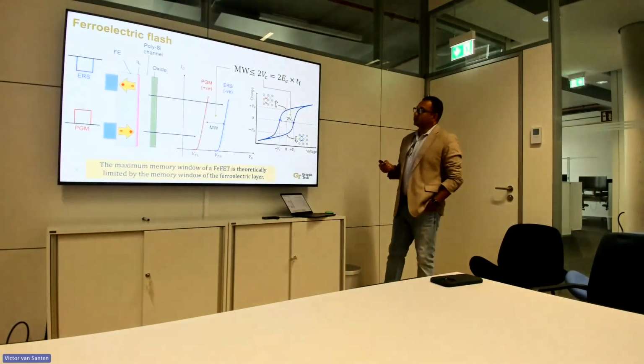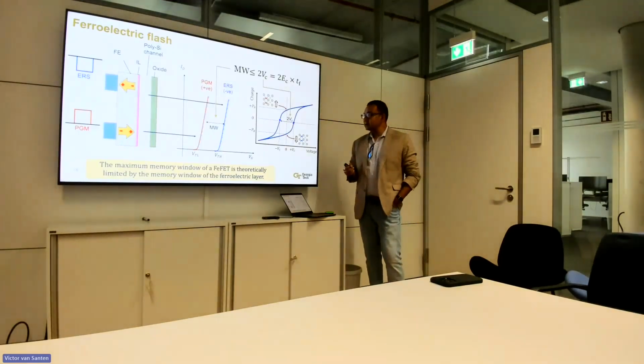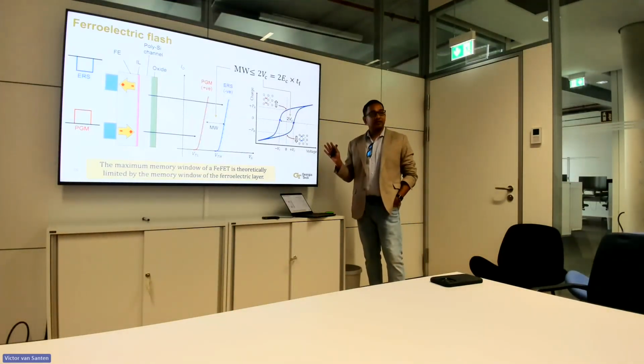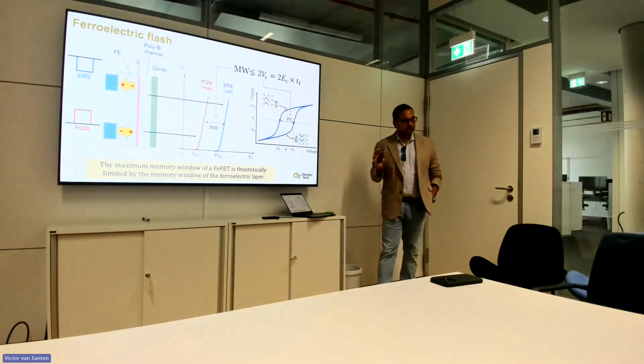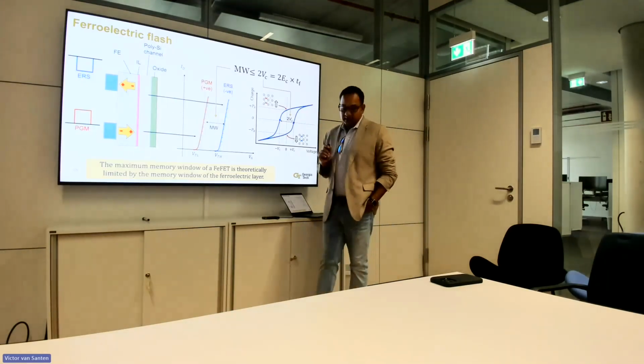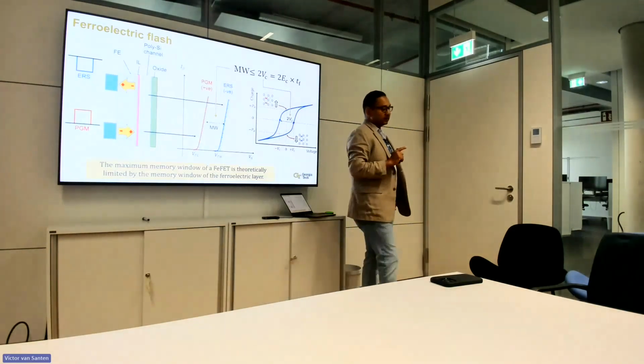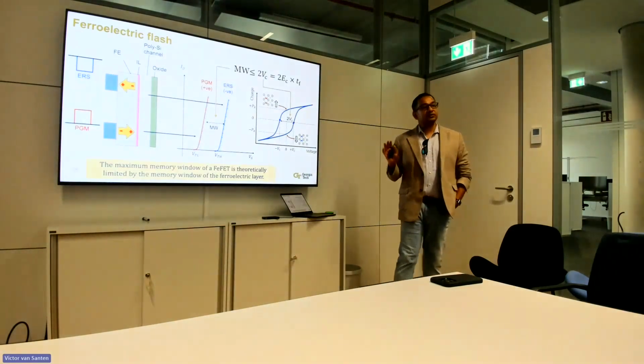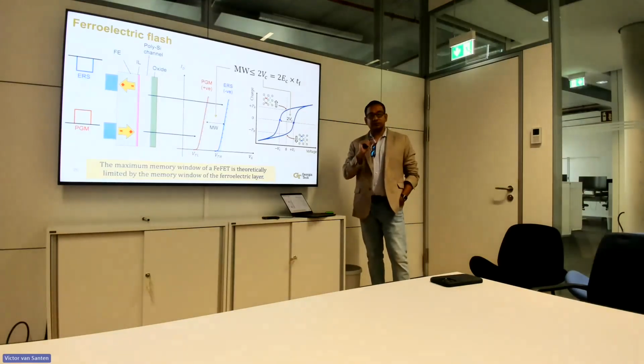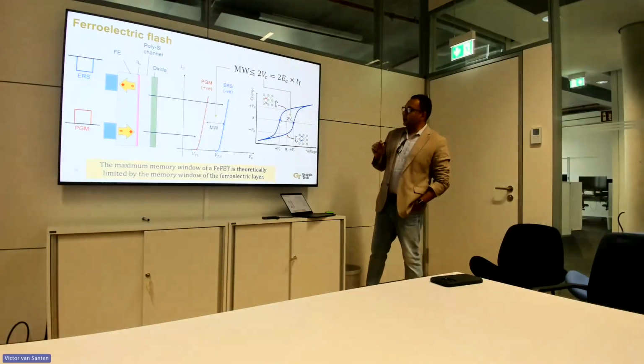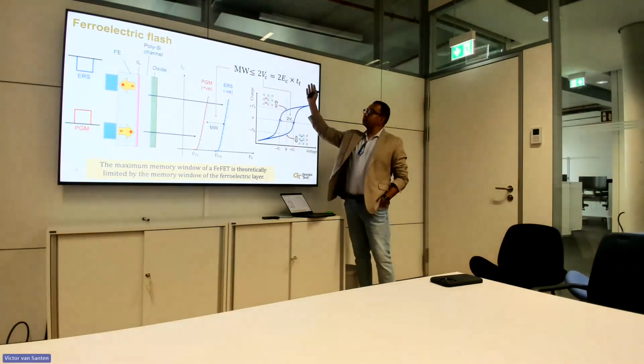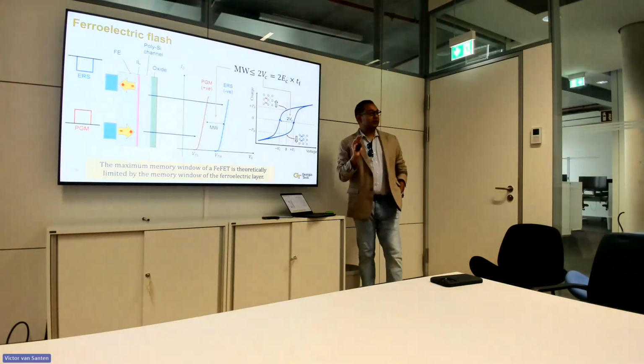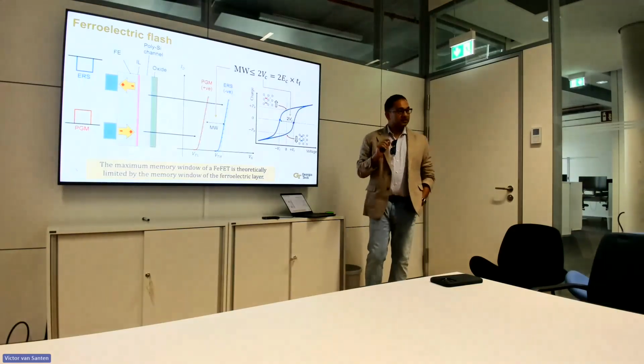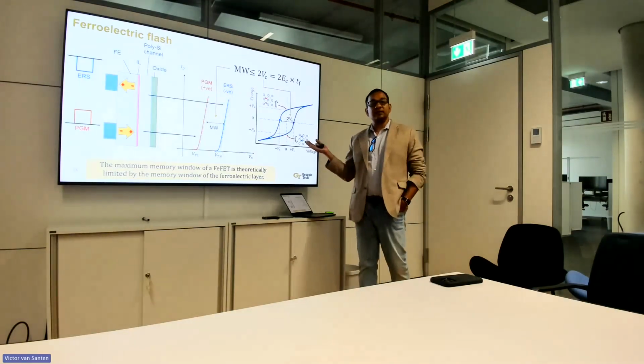Okay, so now before I get into the details, another thing is, what is the maximum limit of memory window that you can get out of a ferroelectric field effect transistor? The key thing here is that we want 7 or 6 volts of memory window with 20 nanometers of ferroelectric thickness. Now, for a long time, it has been known that the maximum memory window that you can get out of a ferroelectric field effect transistor is 2 times the coercive field times the thickness.